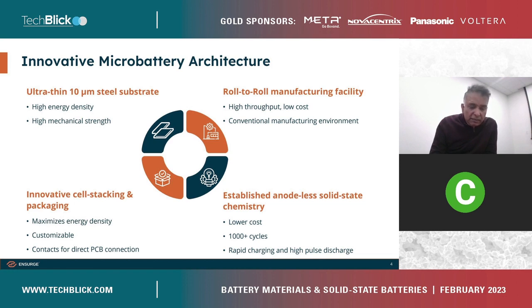And that's the last part of the foundation: in order to maintain, again, the high volumetric energy density, apart from the substrate, which must be as thin as possible, we also have to have very thin overlayers of packaging, which must maintain a seal so that it does not allow moisture, etc., to start to come in. And so it is critical to have low substrate thickness and lower packaging thickness as these cells are stacked.